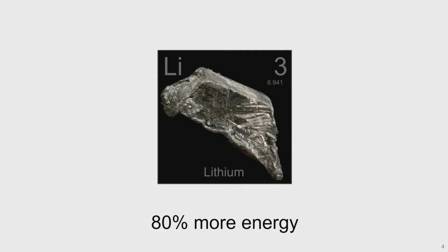So what we're doing is really using much more energy-dense materials. We use a lithium metal battery that's extremely lightweight and ultimately allows us to deliver roughly 80% more energy on the cell level compared to best lithium ion in the world. Today we have 400 watt hours per kilogram in prototypes, and within the next year or so, we're anticipating getting to 450 watt hours per kilogram. So substantially more energy per weight compared to lithium ion.